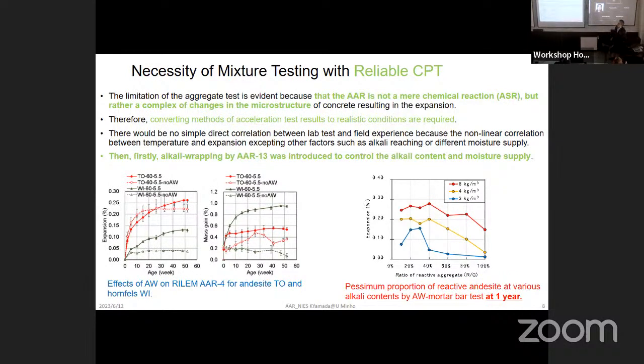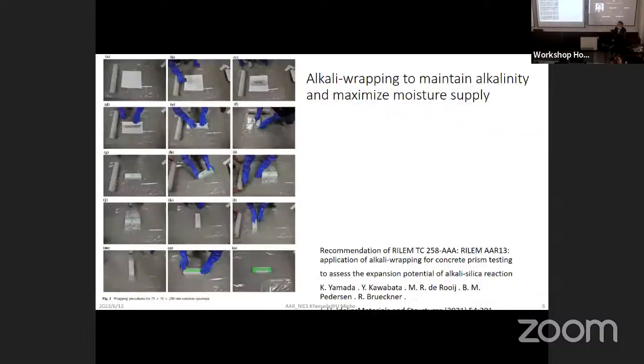But please imagine, the concrete prism is removed from the chamber to some measurement place. Then hot concrete is moved to some cool place, then returned to the hot place. What happens? Water accumulated when cooled. Then water dissolves the alkalis, removing alkali from the prism. So in order to avoid this, we propose one method that's called alkali wrapping.